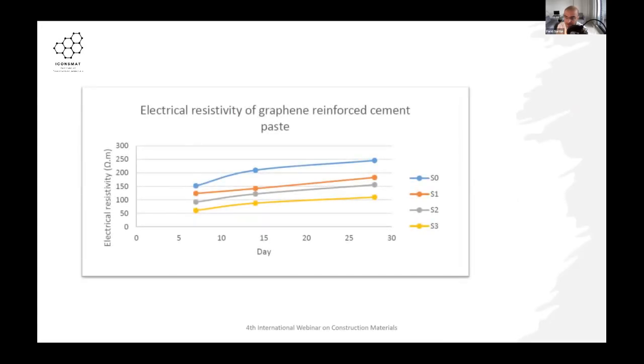As expected, the samples with a higher portion of graphene oxide recorded a higher electrical conductivity, or in this case, lower resistivity. However, it is not rational to increase the portion of graphene in the mix due to many reasons, the most obvious one being the cost, and the second reason that comes to mind is the uncertainties around the corrosion rate. Regardless, being able to produce graphene oxide is being considered as a technological advancement for the material industry.